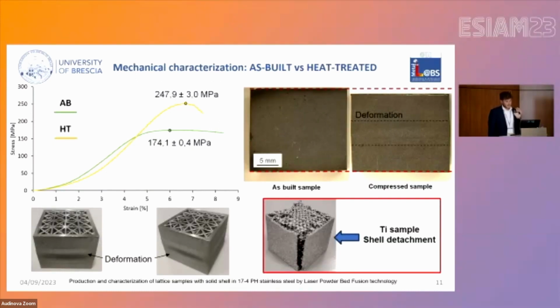But the very important thing in this study was the deformation, because in this case we obtain a deformation of the shell that follows the compression. So we don't obtain a detachment of the shell like I obtained in another study for the titanium sample, as you can see in this picture, because here we applied the same compression test, but we obtained that the lattice, the internal structure, expanded in the external direction and detached the solid shell from the structure. Instead, in the case of 17-4 PH, we obtain a deformation of the shell. And so we understand that we can use the 17-4 PH with higher load and, for example, this titanium with lower load, and for different applications. For example, 17-4 PH can probably be used for shock absorption.